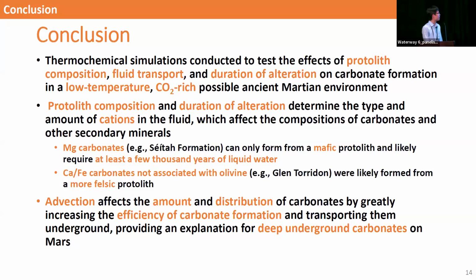Also, calcium iron rich carbonates that are not associated with olivine were likely formed from a more felsic protolith. And for the effect of advection, we found that advection affects the amount and distribution of carbonates by greatly increasing the efficiency of carbonate formation and also providing a mechanism for the formation of deep underground carbonates on Mars.